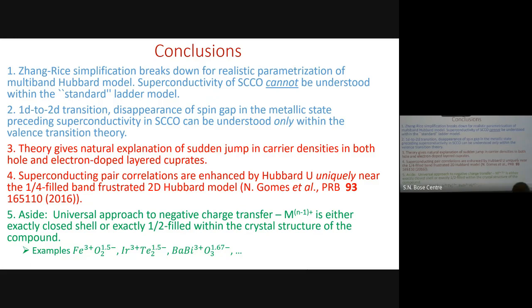But isn't it in some XAS that they see really a split peak in the edge? Sorry? In the X-ray absorption spectroscopy, yes, there is a strong signature of oxygen's contribution in terms of the pre-peak in the oxygen edge. Yes. But that's not quantitative. That was what was used to say that the doped holes are going to oxygen. Yes, absolutely. That they're leading to a valence transition. But it was not quantitative.